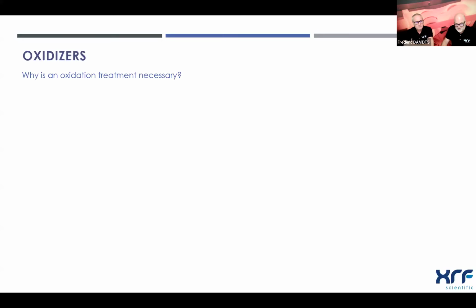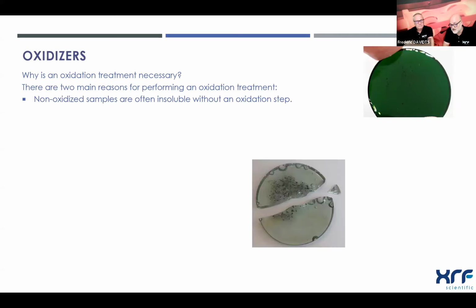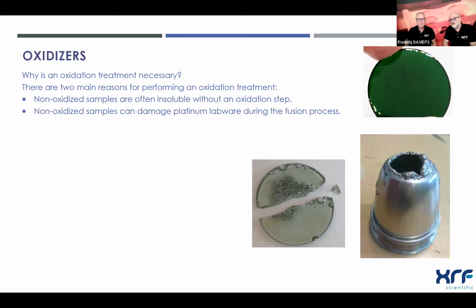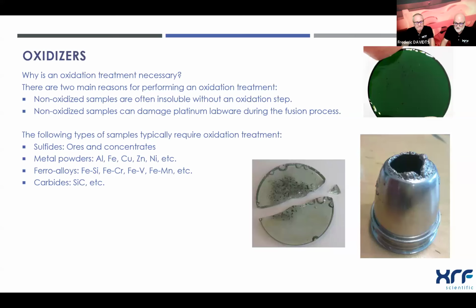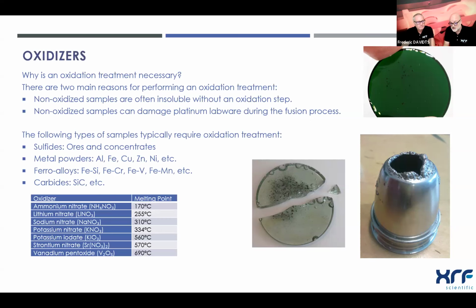The oxidizer, like Paul already explained, is really important for many reasons. First, because the non-fully oxidized samples are insoluble in the bead, so of course you don't have the complete analysis, or even the bead cracks. And also because they are a poison for the platinum labware. And so it's not, of course, nice to have destroyed platinum. Exactly. The types of product that are insoluble without an oxidation treatment are sulfides, metal powders, ferro-alloys, carbides, and that's the list of the most used oxidizers.